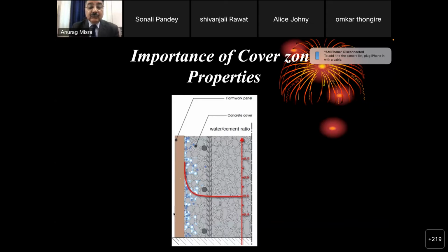So the effective water cement ratio, if we observe, is popularly depicted something like this: the water cement ratio in the outer cover zone becomes quite high as compared to the lower one. So suppose someone used 0.45 water cement ratio and vibrated the concrete. During the vibration, more water is trapped here in the cover zone. So the effective water cement ratio becomes quite high here, and some of the water is going from this mass core concrete outside, so it might be slightly lesser than what you use because more water is accumulated here.